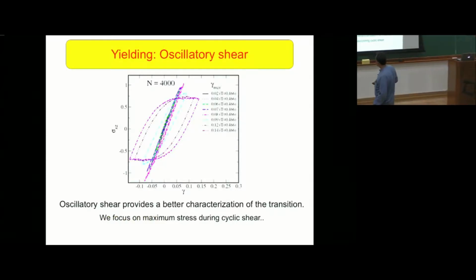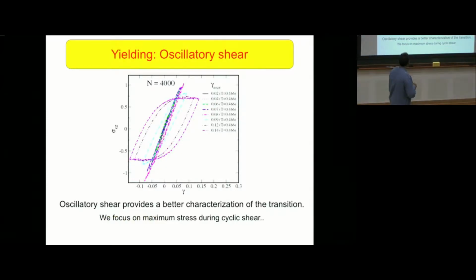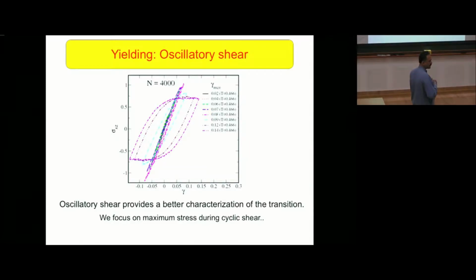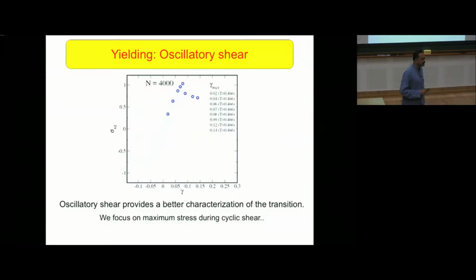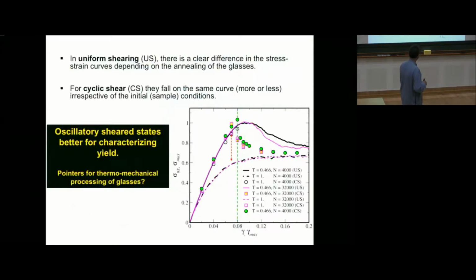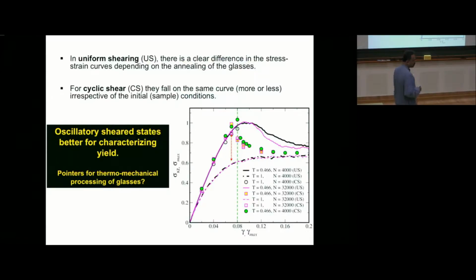So can you do better by looking at oscillatory deformation? And this is now the stress strain curves you find when you do oscillatory deformation. And so here, in order to talk about a transition, you say, let me look at the maximum stress that I developed for any given amplitude of strain. And those are those points, right? And you can see that, in fact, there is something like an elastic branch, but there's a very clear point at which a transition happens, and it's a sharply defined point. There are various details about this, but I'm running short of time.